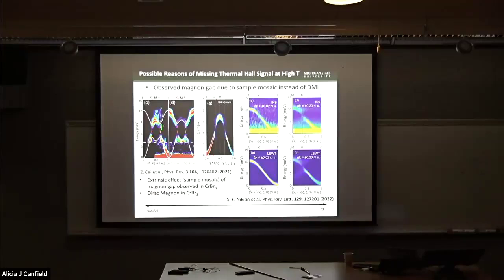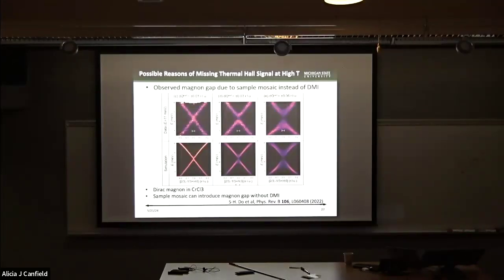Again, in 2021, there was a paper published in PRB which observed a magnon gap at the K point, and they argued that this system shows topological magnetic excitations. One year later, there was another paper by Gruber at PSI, who measured a single piece of chromium tribromide. They did not observe any magnon gap. Okay. So again, the magnon gap opening at the K point would come from the sample mosaic. And a similar conclusion has been reached by a group at Oak Ridge National Lab on chromium trichloride. They observed the Dirac magnons instead of a topological magnon insulator.